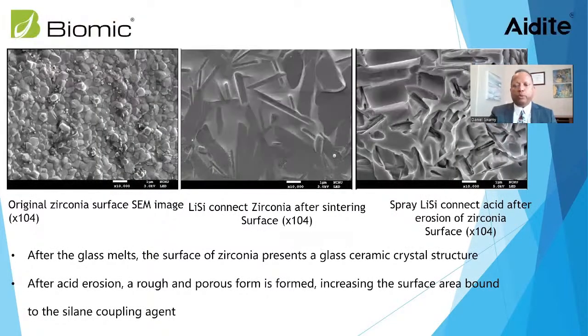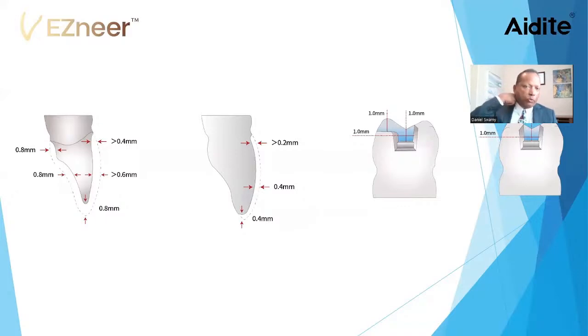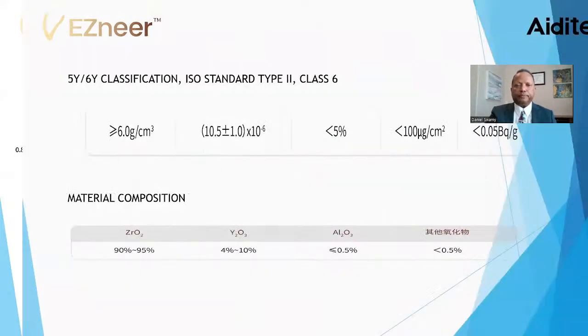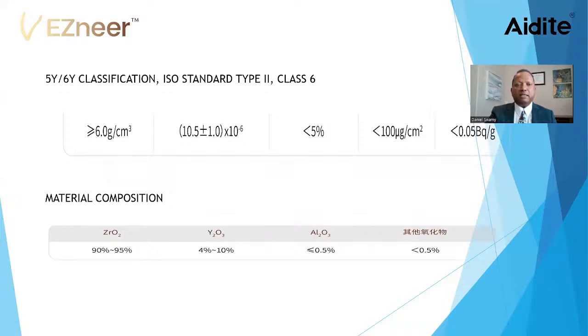Okay. Here are the patterns that we've actually looked at under the scanning electron microscope. You can see that it does form very nice etchable surfaces. Again, we want to advocate that you do a very thin preparation. You can do 0.4 millimeter in the axial walls, 0.2 in the cervical, and 0.4 in the incisal area. Classification is class 6. We're using 5Y and 6Y zirconia, and it falls under the classification of type 2 class 6.